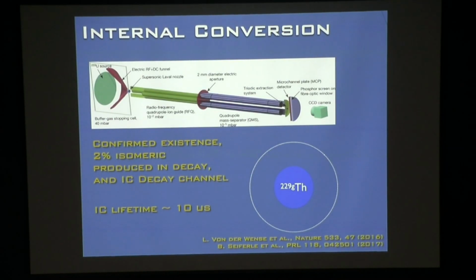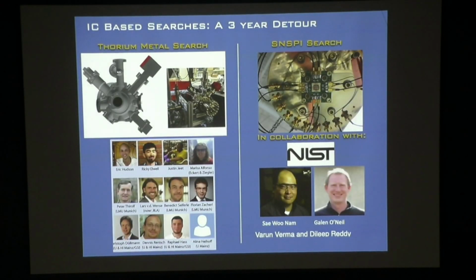Before this, which was not that long ago, a lot of people didn't believe the state even existed. And it also told us that this IC process worked. So we set off to do 2 experiments because we thought, okay, the crystal approach isn't going to work. I won't talk about them in detail. I'll just say that there's an experiment that's very similar to the crystal approach, except it's effectively a thorium metal as the target. And the idea is that you can get enough light into the first little bit to excite some nuclei. They will then emit these internal conversion electrons with a 10 microsecond delay, and you can see the transition.